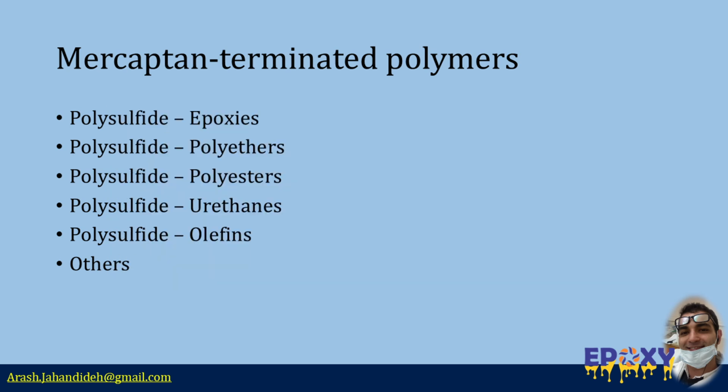For example, polymers have been synthesized with polyoxyalkylene backbones that are terminated with mercaptan groups. This is typically achieved by esterifying polyols with thio-substituted organic acids. Such polymers can be effectively cured using agents like tetramethyl thiuram disulfide and manganese dioxide.